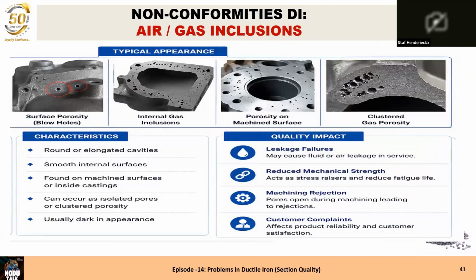On the left side there is surface porosity. We have said now it should be in the section. The second one is an internal one that's coming out when it's machined. The third one is the same. It's coming out when it's machined. And you can have a cluster of gas. When you have that, then it's mostly about a core or a mold that makes a lot of gas in a concentrated area, and there it comes out, and the rest of the casting is fairly good, but somewhere it's due to burning of the mold or mainly the core.